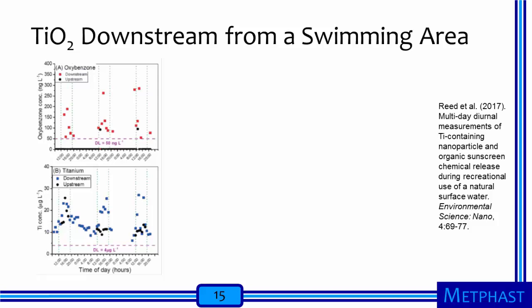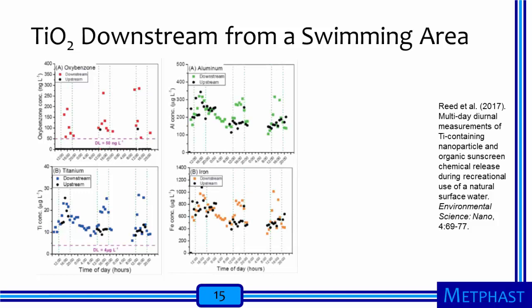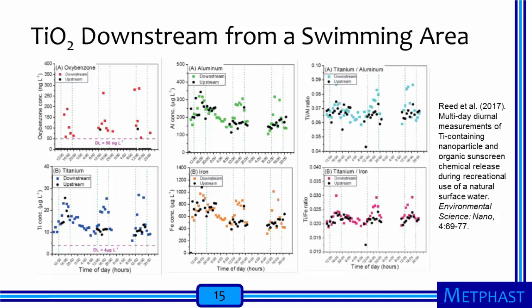The authors recognized that the elevated titanium could be a result of activity in the swimming area stirring up sediments that contain titanium. In these additional figures, the authors were also able to find higher levels of aluminum in green and iron in yellow downstream from the swimming area than upstream. However, when the authors compared upstream and downstream ratios of titanium to aluminum concentrations in light blue and titanium to iron concentrations in pink, they observed higher ratios downstream than upstream, suggesting that at least some of the elevated titanium is caused by releases of titanium dioxide nanoparticles from sunscreens applied by swimmers.